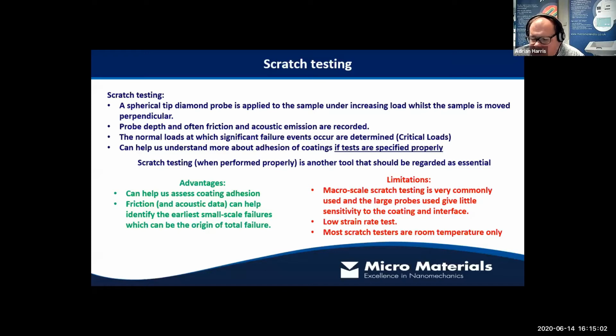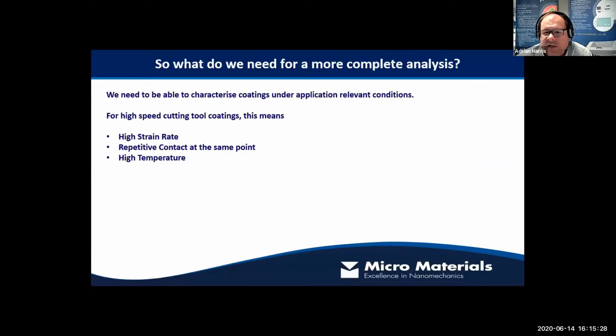It's a low strain rate test, so similar to indentation. It's subjecting the material to deformation at very, very low rates of strain, which are not reflective of the conditions that these materials will have to work under in the surface. Most scratch testers are room temperature only. So again, we're missing slightly the optimum experiment design conditions. So what do we need for a more complete analysis?